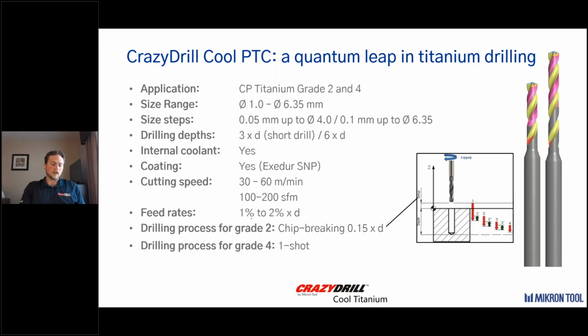We look at ATC. ATC is a family right now to 10 times D with plans to extend longer to match our other drilling lines. PTC stops at 6 times diameter, and we have no plans to extend this. A common question I get is, why is this so? Pure titanium applications are generally dealing with bone plates or shallow holes. In the case of shallow holes or thin-walled plating applications, we don't need to take that drill any further past that. You're generally not seeing large components or deep bores generated in pure titanium. So this family stops at 6 times D.